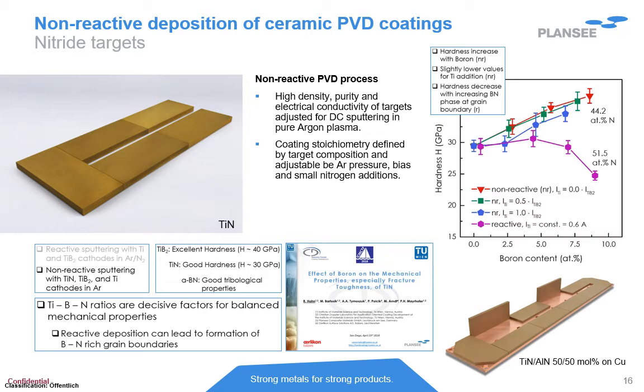Let us study the idea of the following experiment. In the work of Rainer Hahn from Vienna University, titanium boron nitride was deposited in the first trial using titanium and titanium diboride targets in reactive nitrogen-containing plasma. In the second experiment, the titanium boron nitride coating was deposited in pure argon using titanium, titanium diboride, and titanium nitride targets.